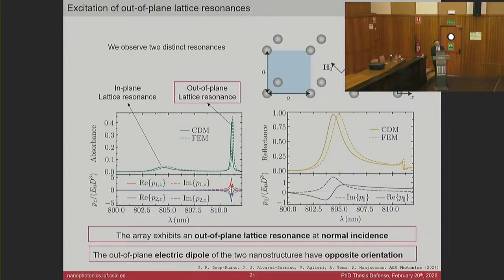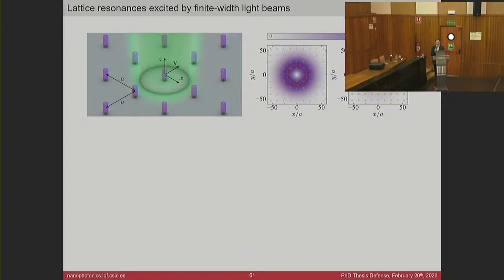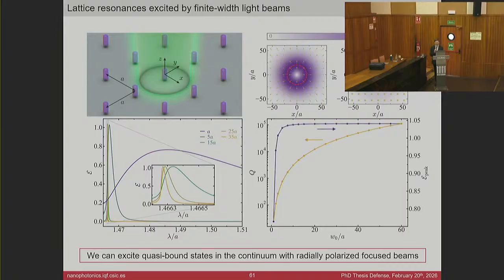I think this case was the optimal one. It will still work, but I think this kind of symmetric case was the optimal one. Yes, we have actually done it in a work that didn't make it to my thesis, led by Luis Cerdan, who is sitting here. Basically, you can structure a light beam such that it has out-of-plane components by using, for example, a radial polarization. In this case, the out-of-plane electric field component of the incident beam will be enough to excite this resonance.